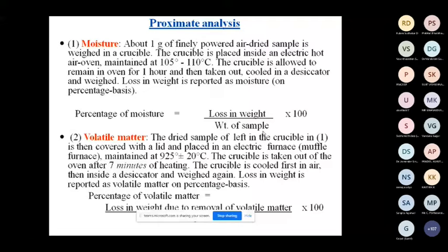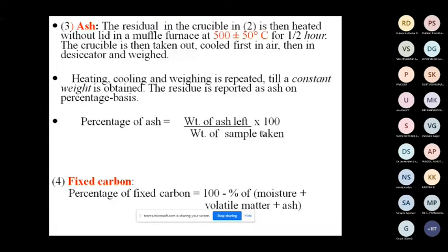Then the third one is ash content. The residual in crucible 2 is then heated in the muffle furnace in an open condition, without lid, at 500 degrees for half an hour. I will explain why 500 degrees. That's the important point.